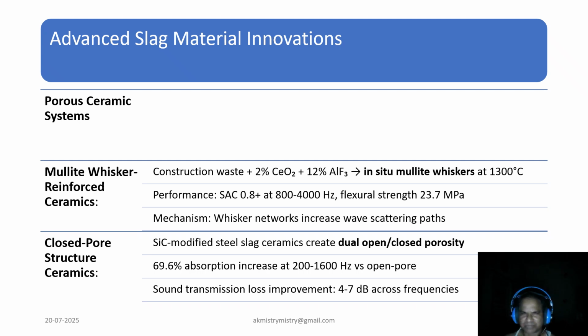A porous ceramic system. This is also a very important thing to be known. Recent breakthroughs have turned steel slag into high function ceramic. For instance, mullite whisker reinforced ceramics crafted from construction waste and additives achieve a sound absorption coefficient above 0.8 at mid-high frequencies, and flexural strength of 23.7 MPa. Meanwhile, silicon carbide modified closed pore structure enhances absorption by nearly 70% in the low frequency range, while reducing sound transmission by up to 7 decibels. These ceramics combine strength and silence.